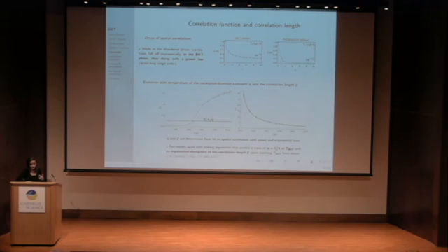So extracting this eta exponent from the power law fit and the correlation length, xi, from the exponential fit, we can track the evolution with temperature of eta and the correlation length. And we find that eta, which should have a value of 1/4 at TBKT, does indeed acquire this value at a temperature that coincides with our previous location of TBKT using the Binder cumulant.